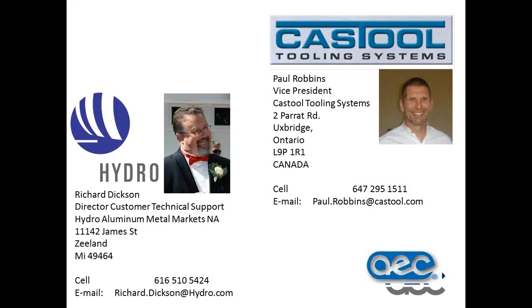I've done some tests way back in my past where we started looking at trying to put a really heavy nitride in on the first time, so that as a die maker, which I was working for Hydro's Die Shop in France, we were trying to produce a die that already had 5 nitridings, so it was perfect for the extruder. This didn't work at all well. We ended up making white layer. We ended up getting all sorts of problems with it. It does seem that nitriding needs to be progressive, and in some ways gently progressive. So you just have to accept that your first 1, 2, 3 nitrides are developing this ideal layer. I don't think it's really very easy without salt baths to jump directly to a good deep layer.